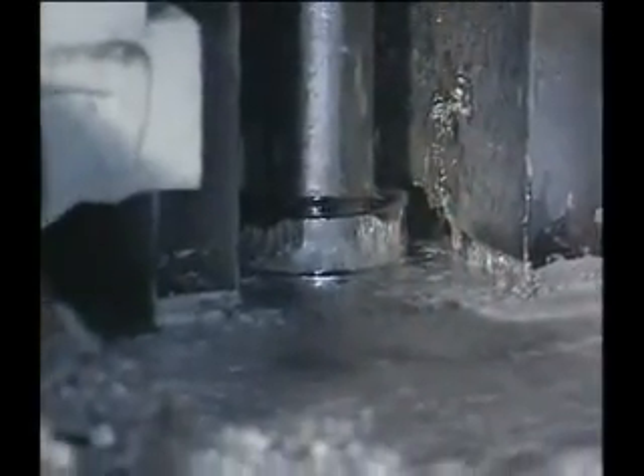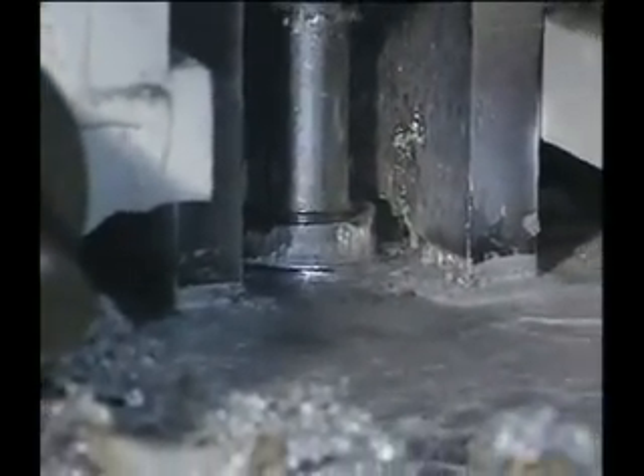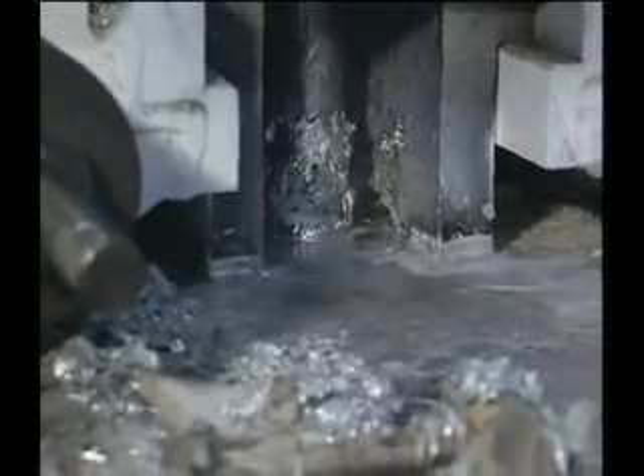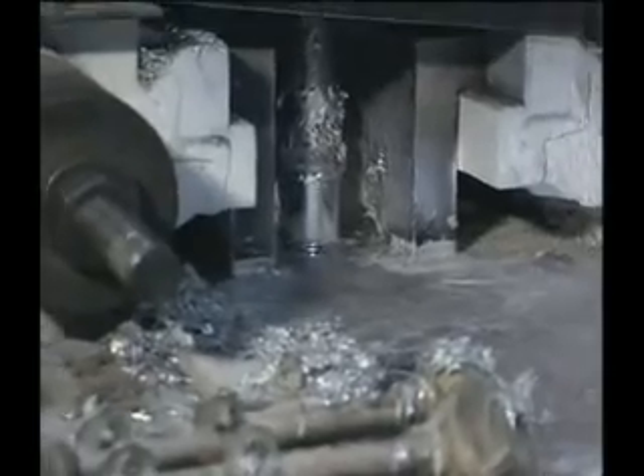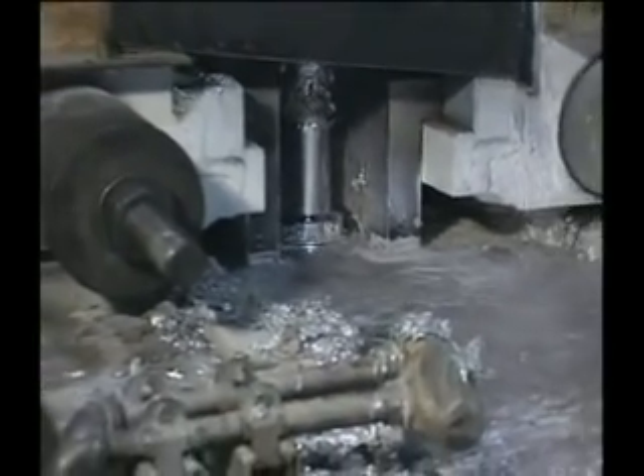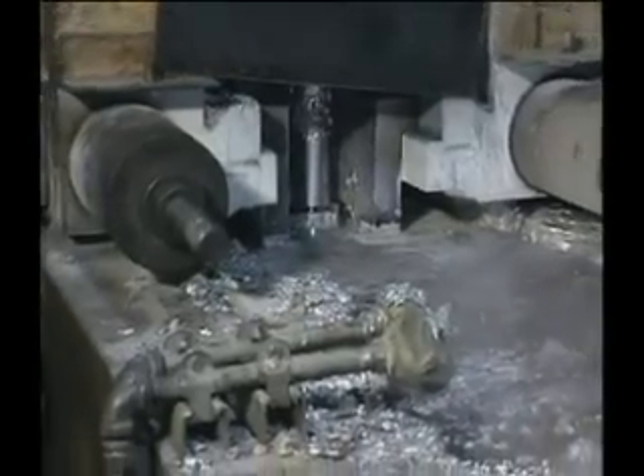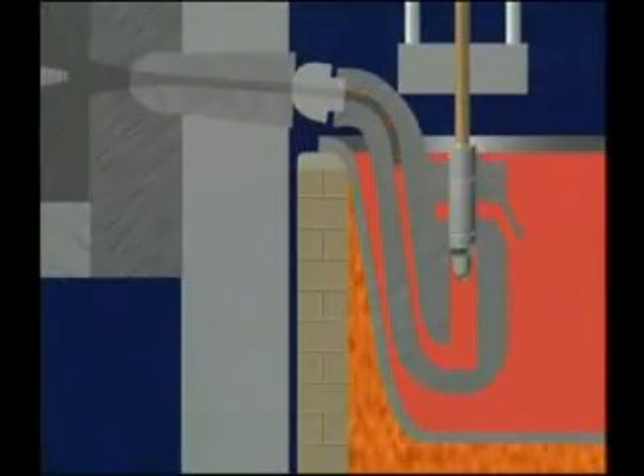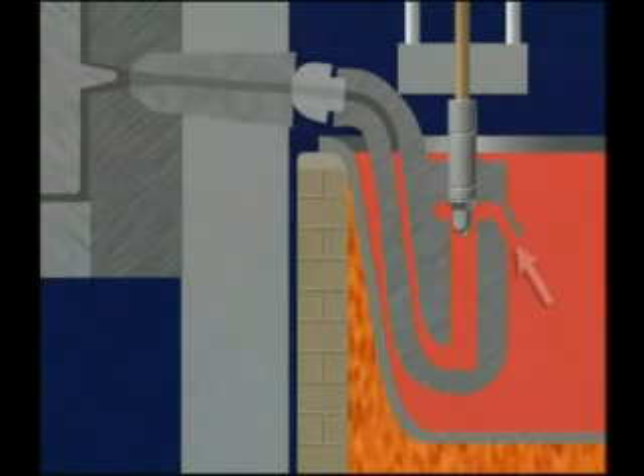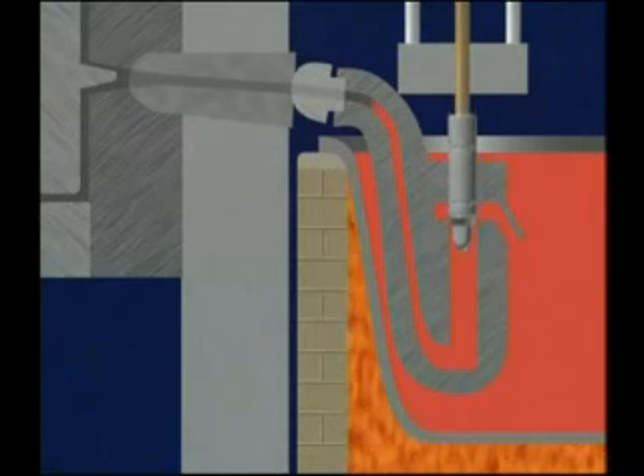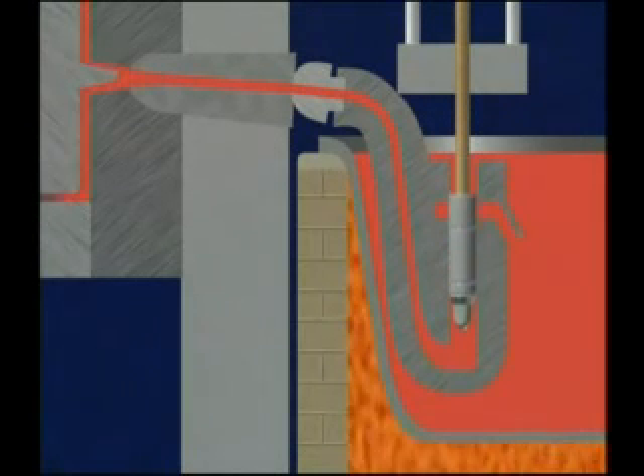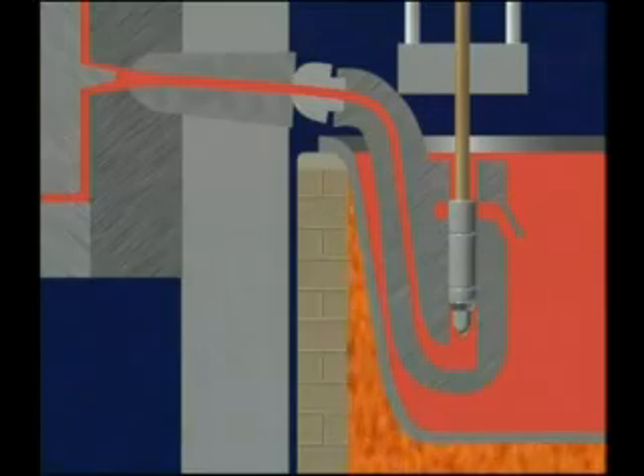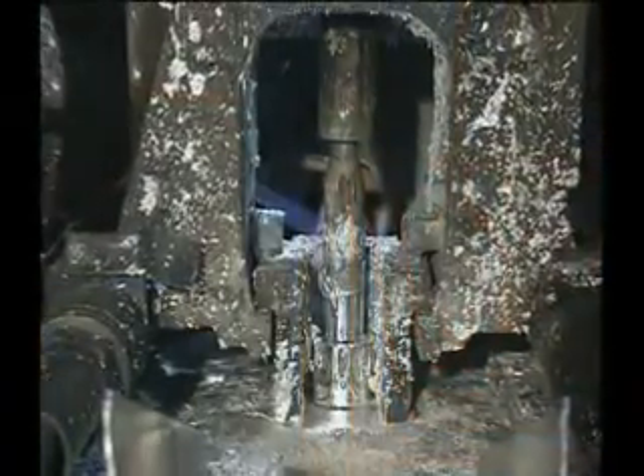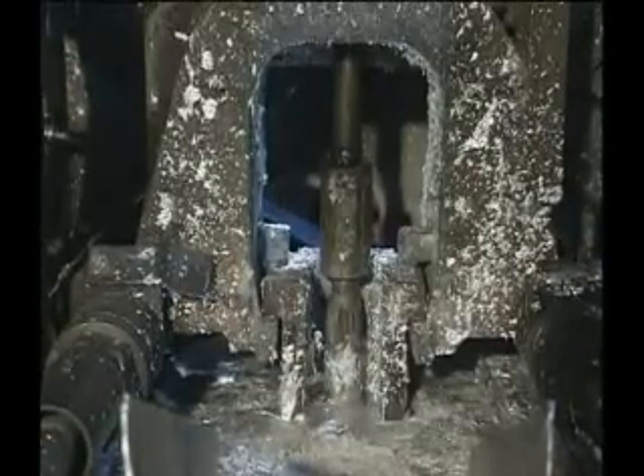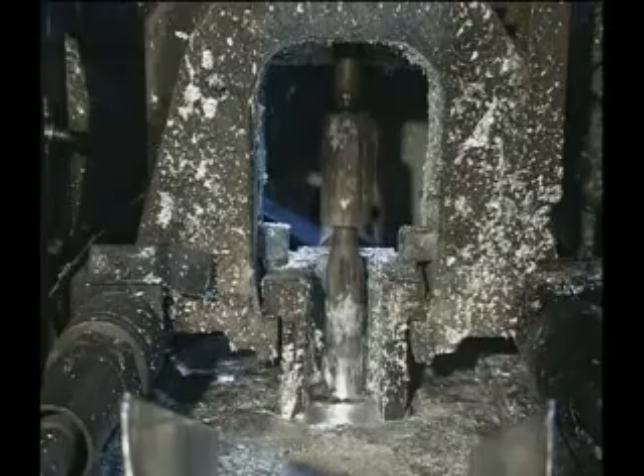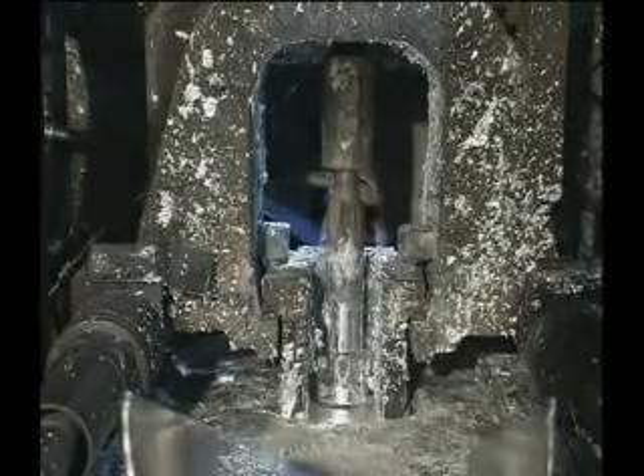The plunger end of the injection system and the lower portion of the transfer pipe are submerged in the molten metal. For this reason, aluminum and copper alloys are unsuitable for use, since they chemically attack or erode the submerged injection system. When the plunger rises, a charge of metal enters the pipe through a port. When the plunger descends, it closes the port and drives the charge through a nozzle at the end of the pipe and into the die. Injection pressures may range from 1,500 to more than 4,500 pounds per square inch, or 10 to 31 megapascals.